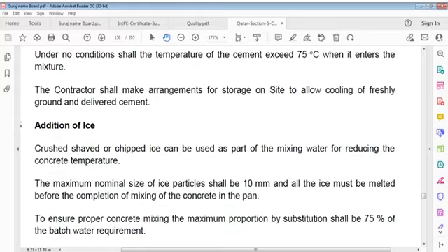Under no condition shall the temperature of cement exceed 75 degrees Celsius. I am repeating it, when it enters the mixture. Contractor shall make arrangements for storage on site to allow cooling of freshly ground and delivered cement.